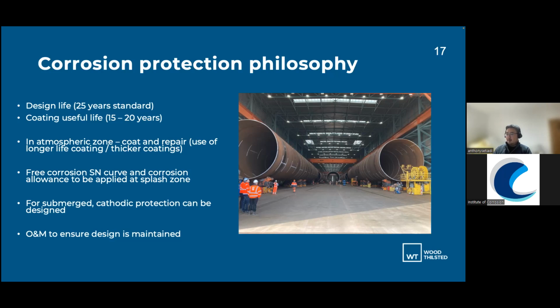There are life extension proposals, which go to about 30 to 35 years, which means you have a longer free corrosion period. For the submerged zone, we can include cathodic protection in there to mitigate some of the penalty that we're going to get for the free corrosion fatigue curves. And then finally, we want to make sure that O&M is there and able to maintain the structures.